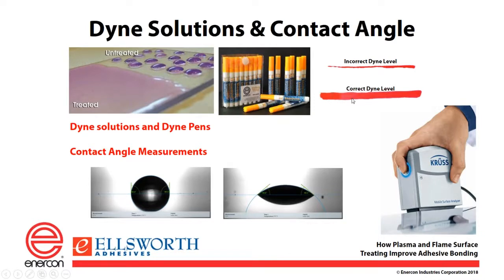If you did 50 Dyne and you got the second trail there and it stayed together for 2 seconds, then you would have said to have passed it at 50 Dyne. So now you know that your surface energy is above 50 Dyne. Contact angle is inversely proportional to Dyne, and it varies by surface. So I can't just give you one graph that shows you what, if you're at so-and-so Dyne, you're at this level of contact angle.